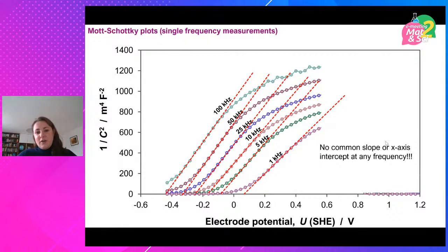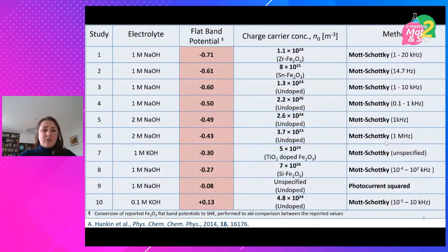So we thought, well, we can't use this. It's just not reasonable. So we then started looking more closely into the literature, and we found that just for synthetic hematite electrodes, so if we just scan the values that are highlighted in red, under the same conditions, over quite a small range of doping densities, the values of the flat band potential, if you convert them to the same reference electrode, they span 0.8 of a volt? I mean, that's a huge dispersion in values. In fact, we thought, well, this renders these values completely meaningless because there's something really wrong here. There cannot be such a dispersion in flat band potentials because it's just not justified by the doping density or the electrolyte compositions, which were more or less the same for all of these systems.